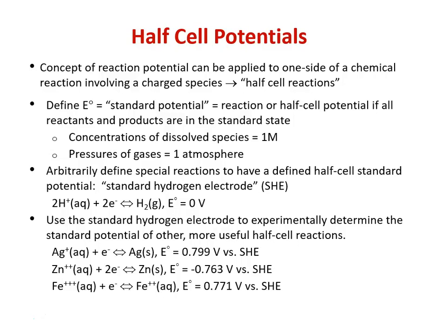We define in electrochemistry and in corrosion a standard potential, which is an analog to this, and all it means is that we have defined some of the thermodynamic state variables involved in the reaction that's going on, namely pressure. So we assume that we have 1 atmosphere of pressure. We assume we have 1 molar concentration of any of our dissolved species, and typically we'll define also room temperature,